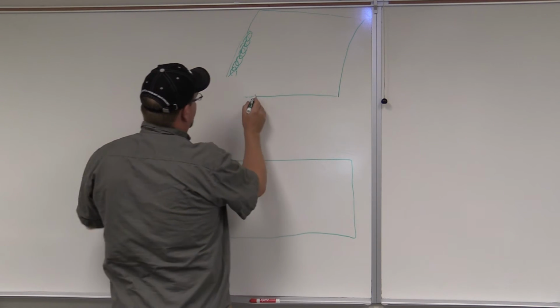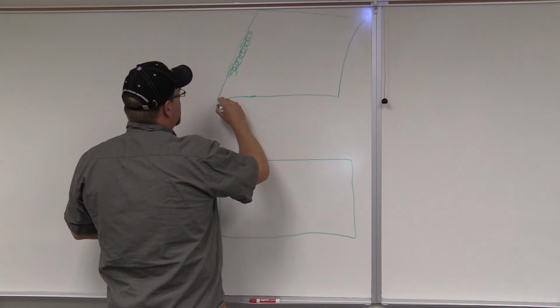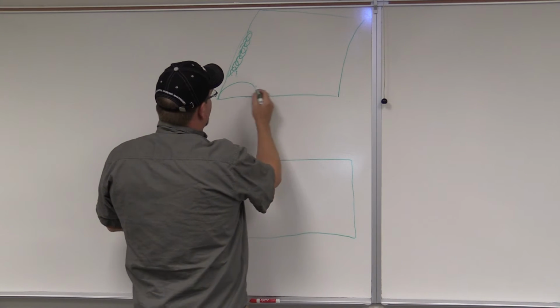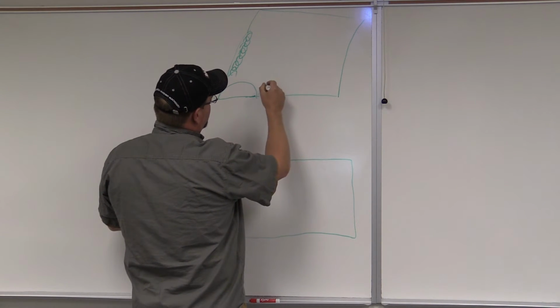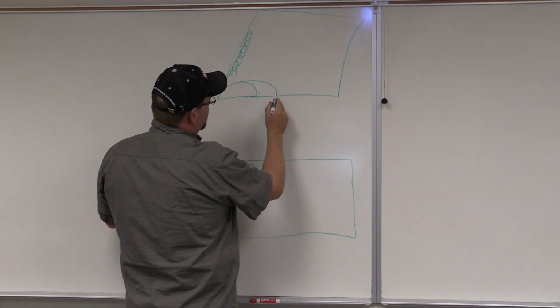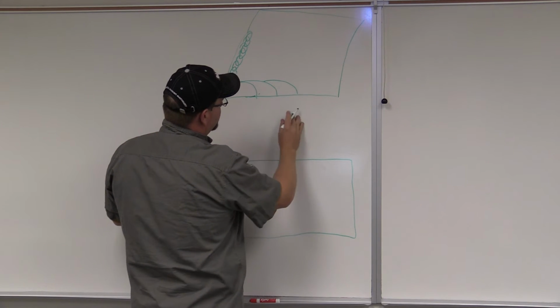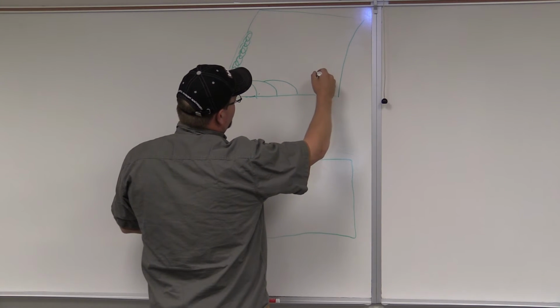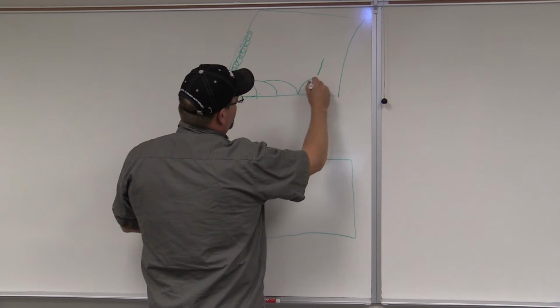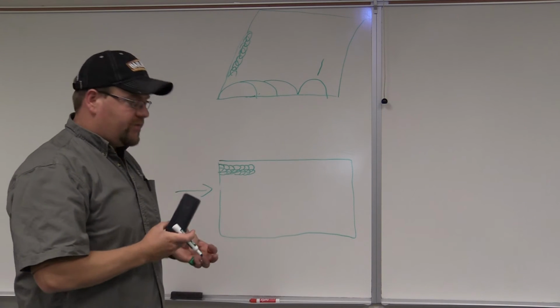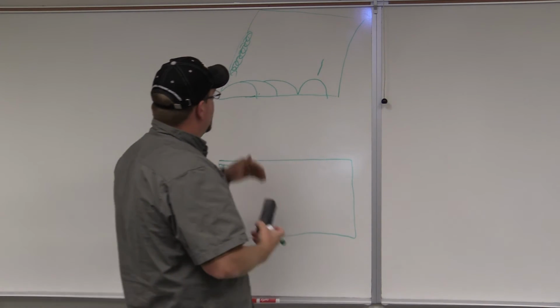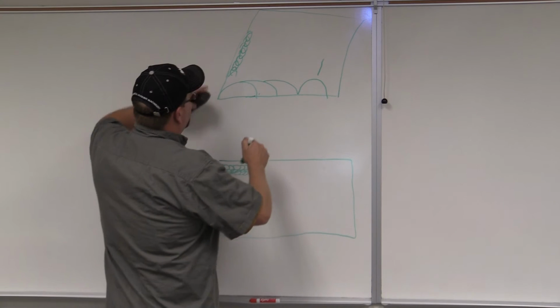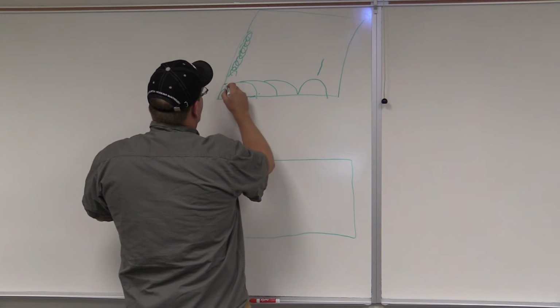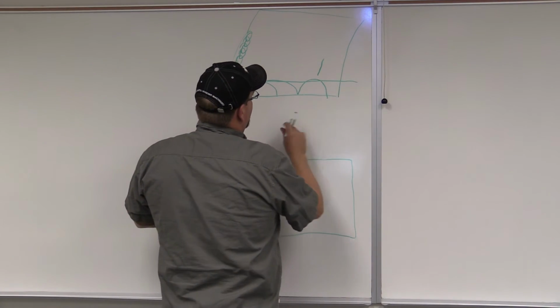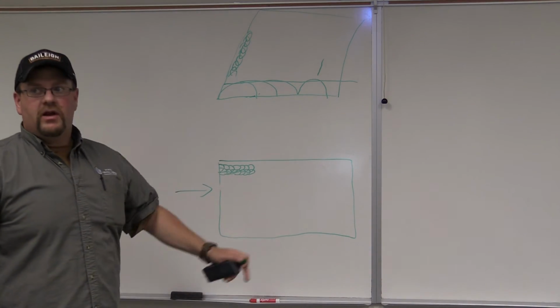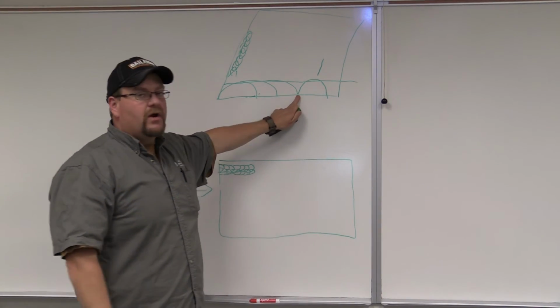Do a larger scale picture here. So this is our weld. We want to make sure that we weld in coming right to the toe of this weld. Make sure that it ties in. What we want to avoid is coming out here and laying a weld bead here. Because then what happens if we were to machine this down or grind it down to prepare this, right here, we've got good solid weld, and then all of a sudden we have a large void in the middle. So we have to come back and repair this.